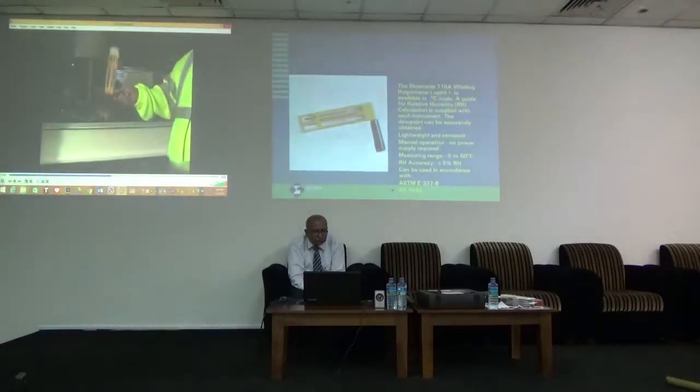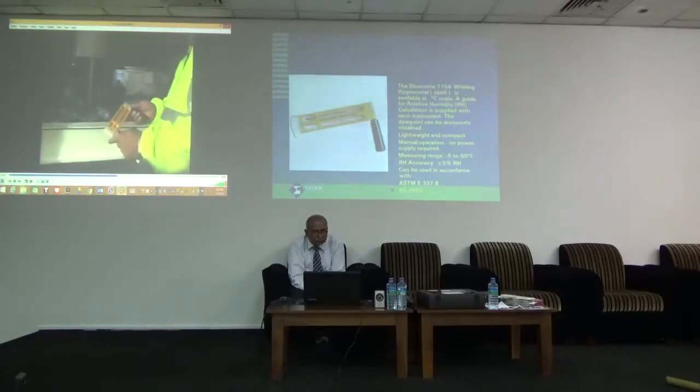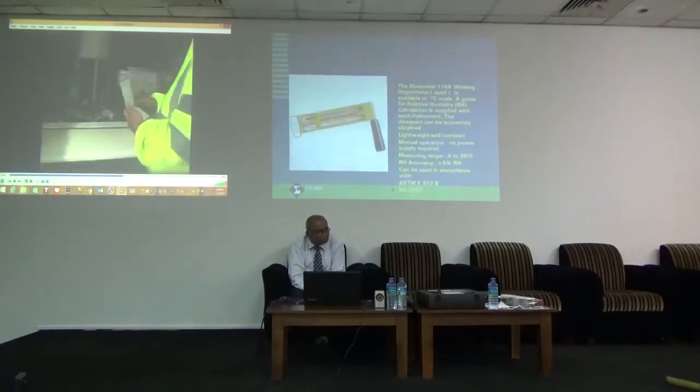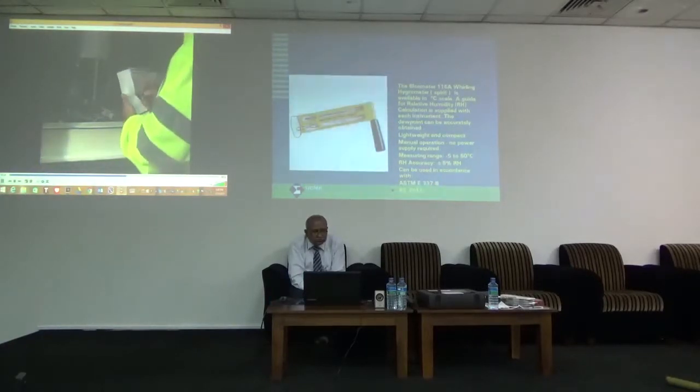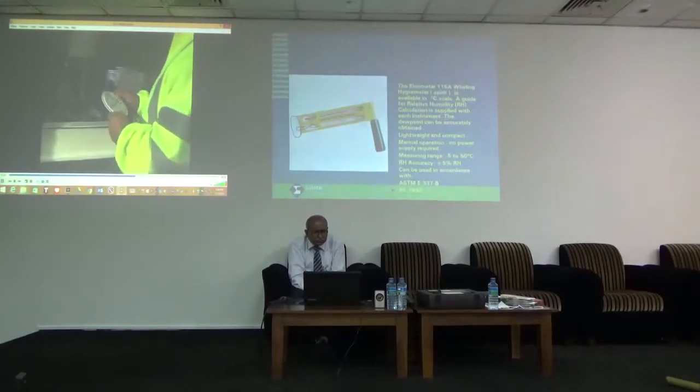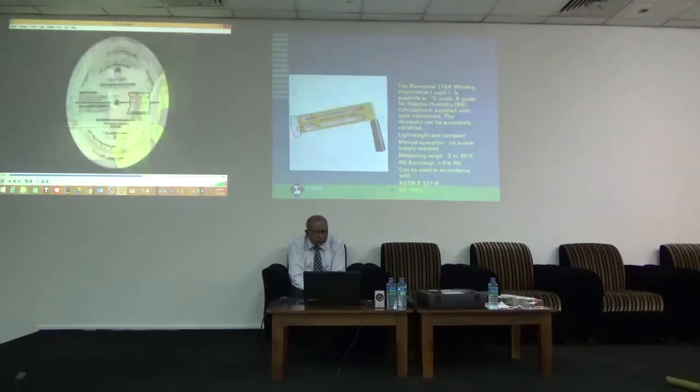Whirl the hygrometer for approximately 30 seconds, keeping it away from your body. Check the temperatures on the wet bulb and then the dry bulb and record the readings. You should conduct 2 or 3 readings to ensure that you get consistent recordings. Once you have the wet and dry bulb temperatures, you can find the relative humidity by using tables or a relative humidity calculator, which will also give you the dew point.